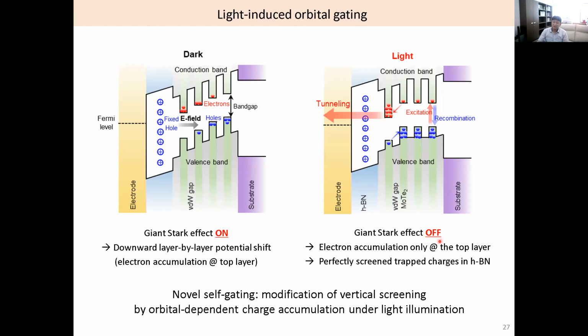So the giant Stark effect always exists, but here "off" means this cross-charge electric field is screened quite well by these accumulated electrons. So this is a new kind of self-gating. This is the first concept that we suggest. If we have this internal potential gradient in a 2D semiconductor, and we make this tunneling electrode, we always have this voltage drop depending on the electron momentum, and we have light illumination, and we have gating only in the top layer. And again, here we have tunneling current.